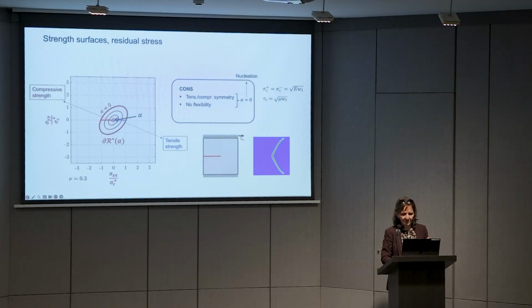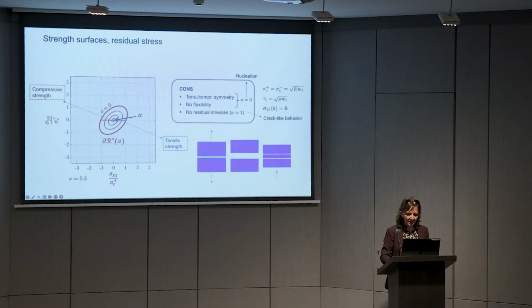For instance, if you run a shear test, you will get 2 cracks, and instead you would like to have the crack only on the tensile part and not on the compressive part. On the other hand, this is also bad for interpenetration because you have a 0 residual stress, and so when you push 2 cracked parts together in compression, then they would penetrate each other. Okay, so this is a bad model.